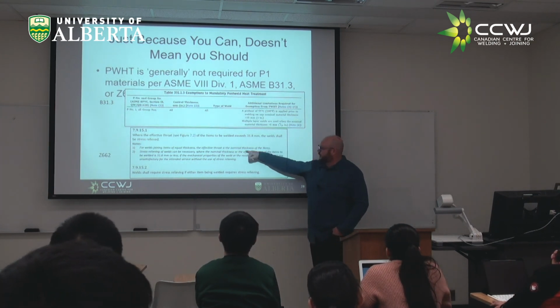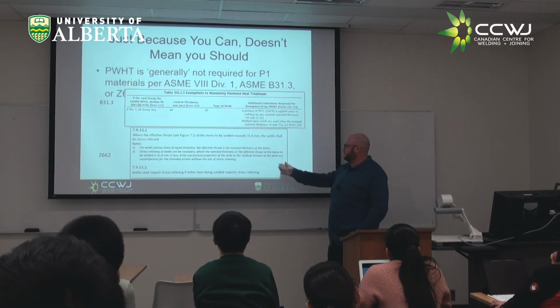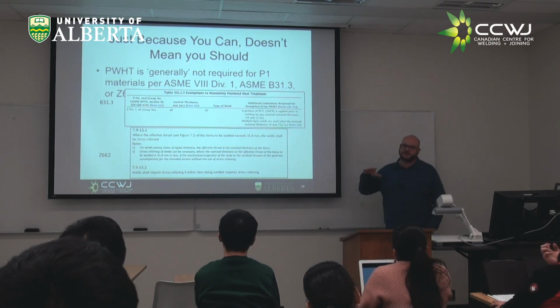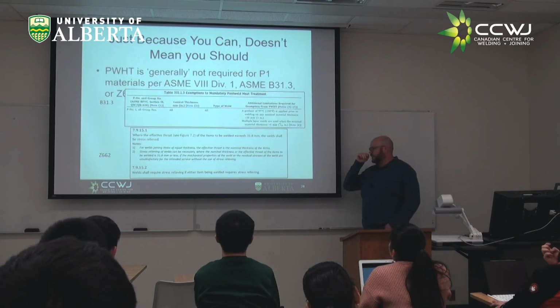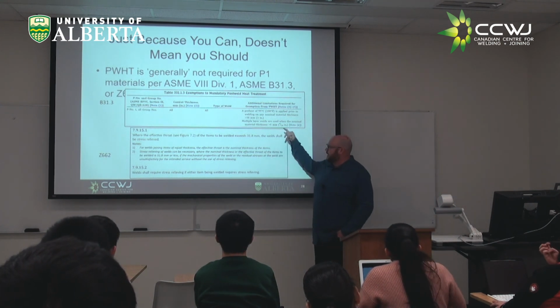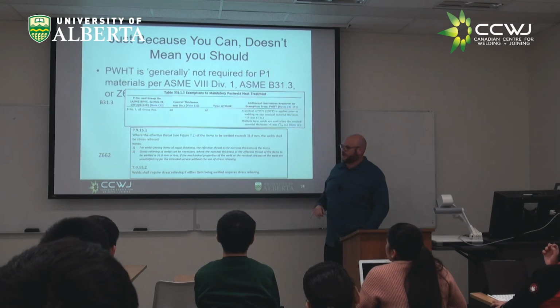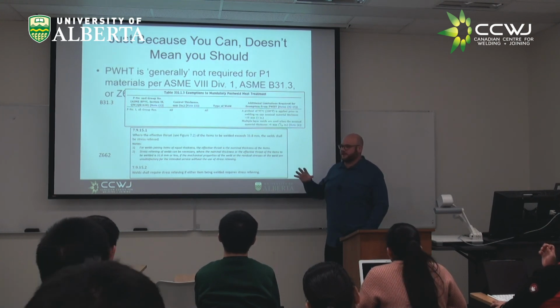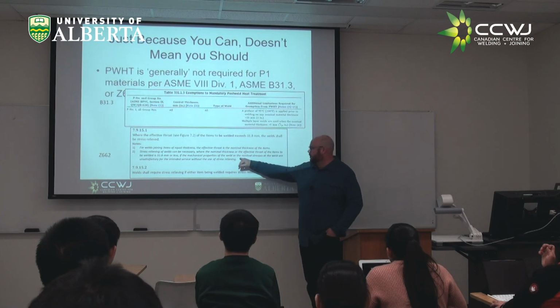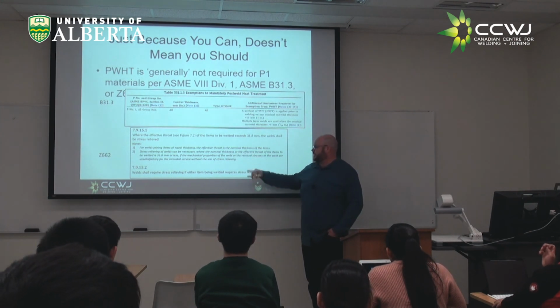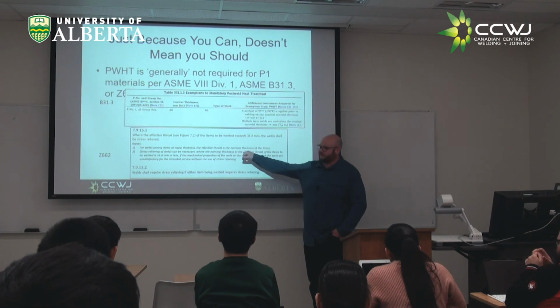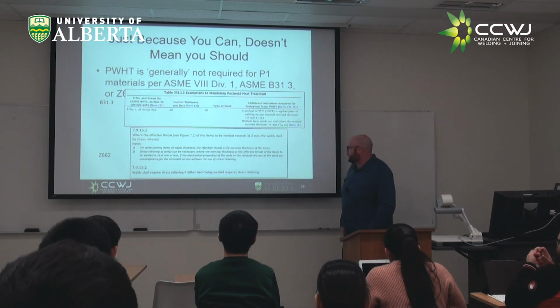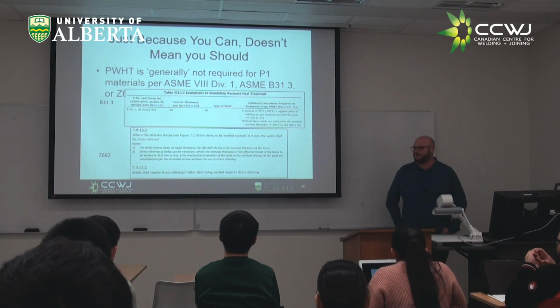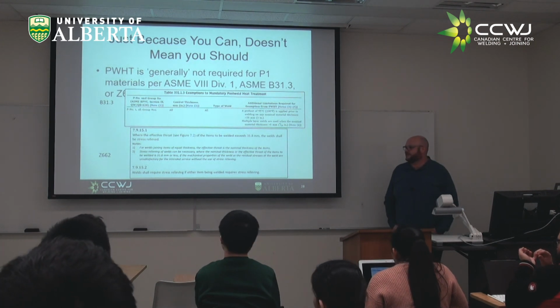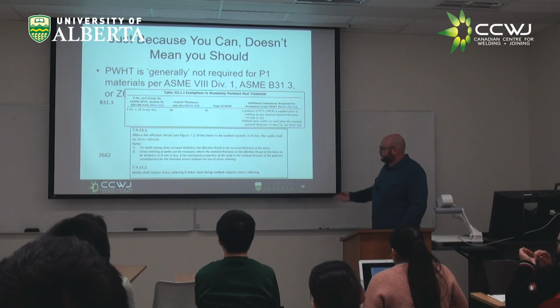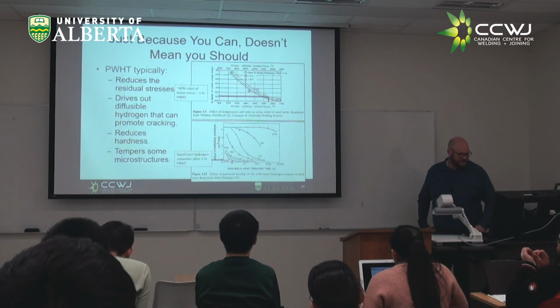The Z662 down here is a little bit more straightforward, where they just say basically you don't have to worry about post-weld heat treatment until you get over 1.25 inches or 31.8 millimeters. But every single code where they provide an exemption will have some variation of language that says except. And CSA is just a little bit more clear. They basically say you don't have to post-weld heat treat unless you have to post-weld heat treat because of the weld properties, residual stresses, or whatnot for the intended service. So anyways, moving on to the next slide.